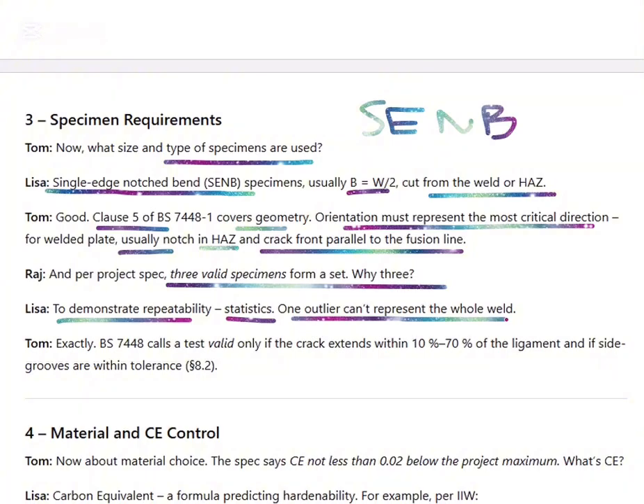One outlier can't represent the whole weld. Exactly. BS 7448 calls a test valid only if the crack extends within 10% to 70% of the ligament, and if side-grooves are within the tolerance.